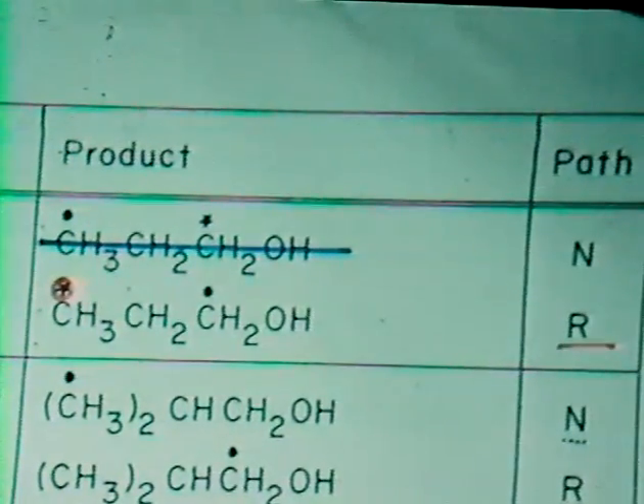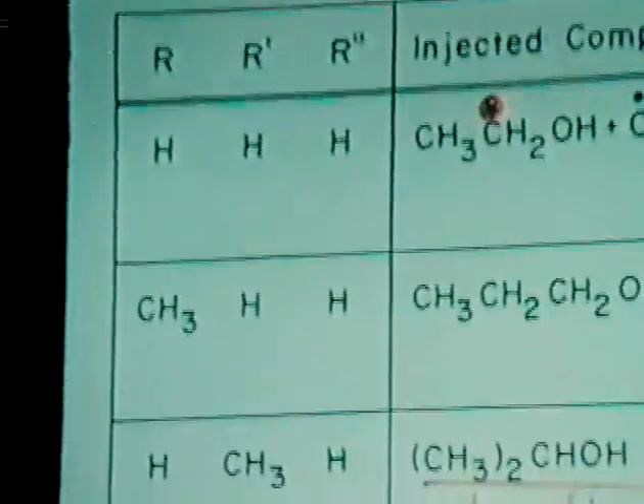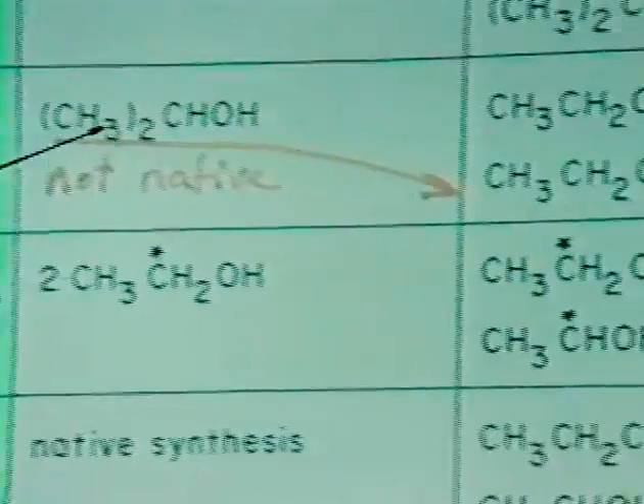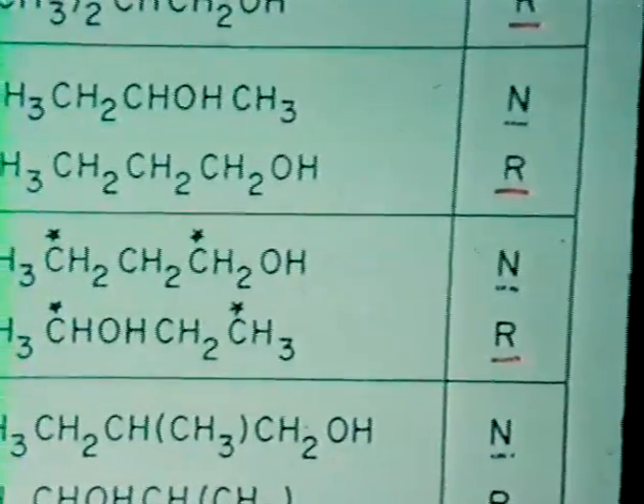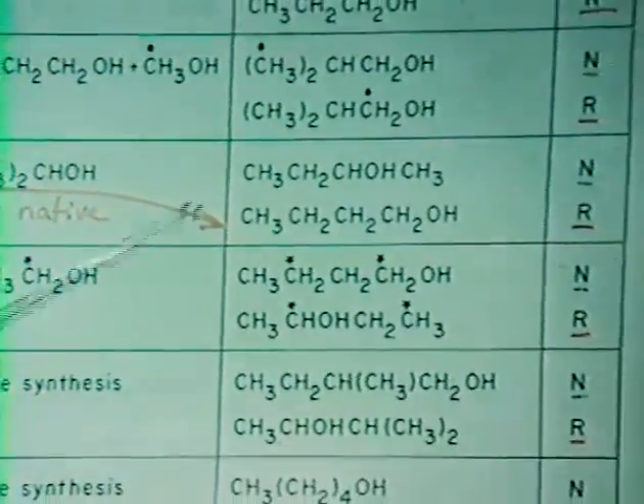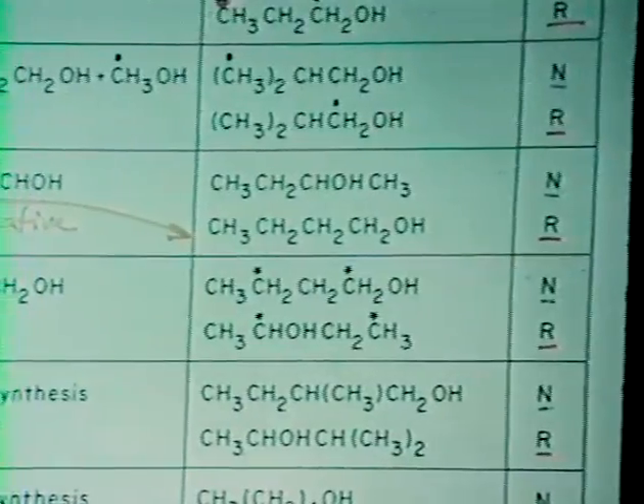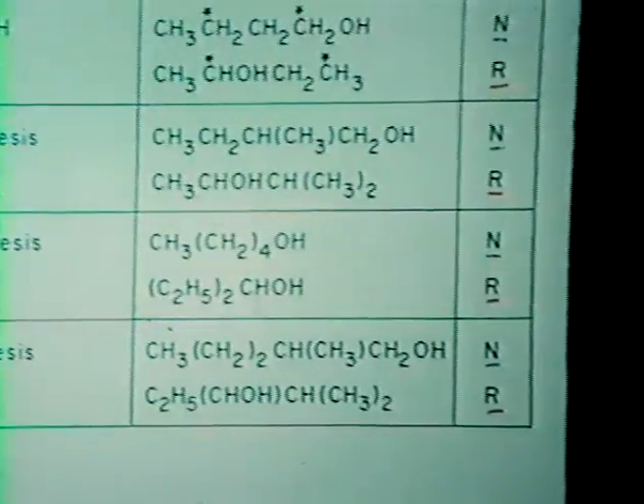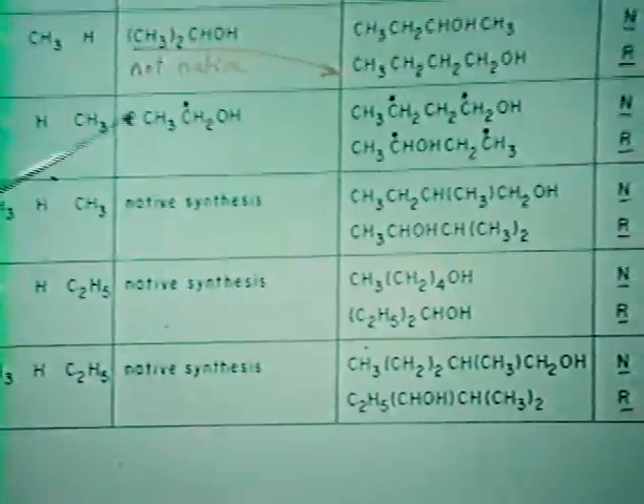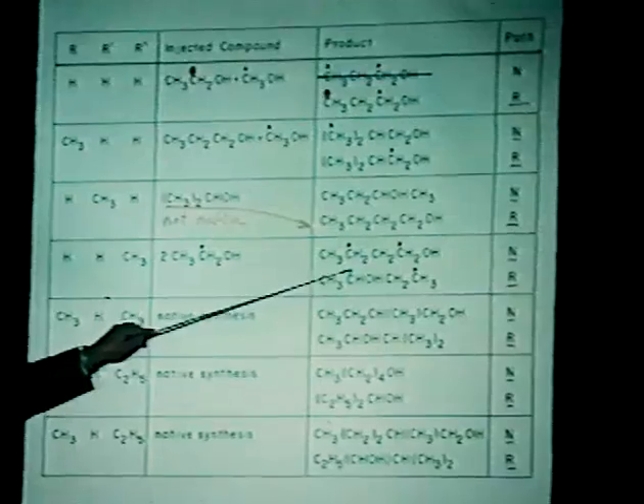Then we can follow the native synthesis, but if we inject an alcohol which is not native, we get a bunch of products which are not normal products of that synthesis. Here we are injecting isopropanol, a secondary propanol, and in fact, if you inject isopropanol and couple it with carbon monoxide and hydrogen, your main product is going to be linear butanol. That's the synthesis pattern, and that product is observed, and in fact isotopic experiments were done for this. There are some more complex reactions in which C2 plus C2 are combining, and we are getting two labels from these and secondary alcohol, as I indicated.